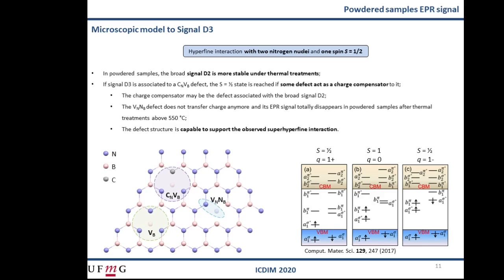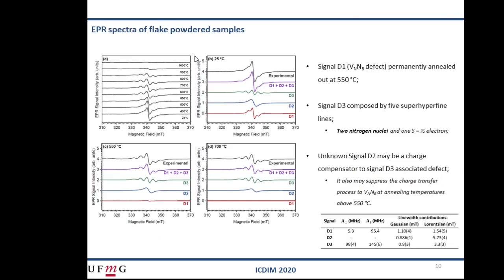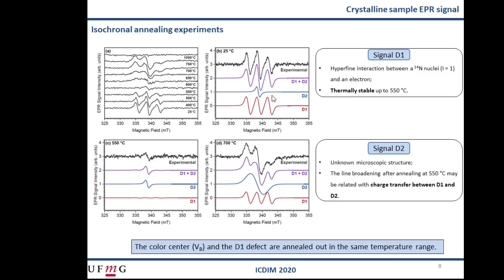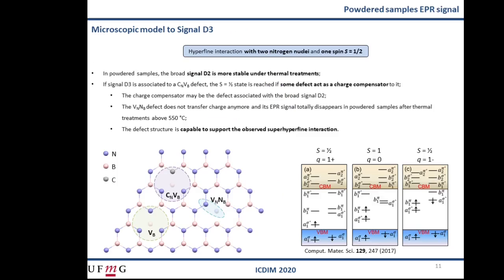The necessity of the CNVB defect to receive or donate an electron to reach the spin one-half state can be used to explain why the EPR signal D2 in powdered samples is more stable than that in the crystalline sample. Remember that the signal D2 in the crystalline sample before the thermal treatments has low intensity and its line width is compared to that of signal D1 here. The signal D2 is weak and its line width is almost the same as D1. After the treatment at 550 degrees, its intensity and line width become bigger, which was interpreted as a consequence of charge transfer between the signals D1 and D2.